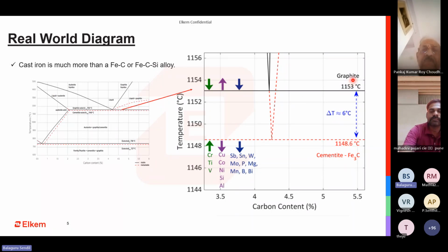So this line here, what you see above, between 1152 and 1154, is the graphite line, and 1150 to 1148 is the carbide cementite line. If I look at the delta T, it is a 6-degree window in which we are operating. This gap can either increase or narrow depending upon the elements that are associated.